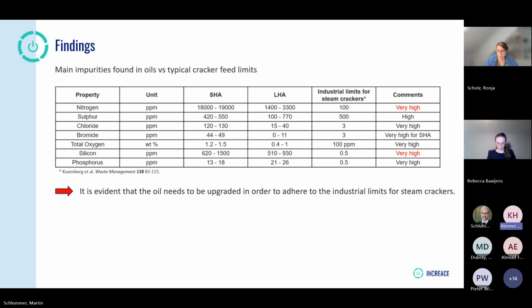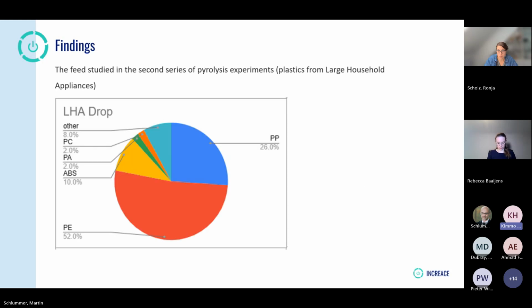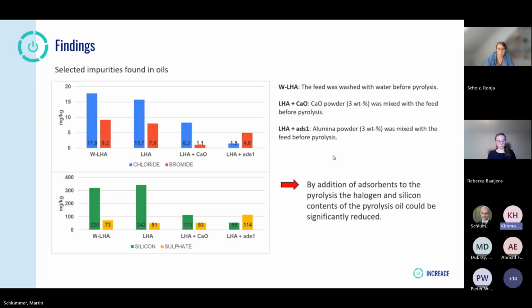And the second example, the feed for the second set of experiments, was from large household appliances. Okay, but this is not the same. This time it's very PE rich, and altogether polyolefins are about 80%, so it's quite suitable. Okay, there's 10% ABS, but it's still manageable. And the next slide is then showing the main results from that.